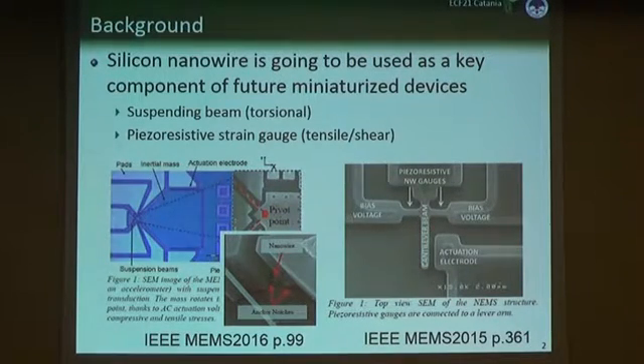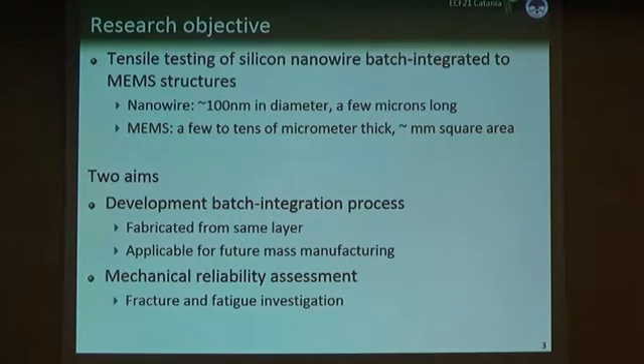In order to evaluate the structural integrity or reliability, we need to investigate the tensile fracture of these nanowires. So our research objective is to do a tensile testing of silicon nanowire, but this nanowire should be fabricated using a MEMS integration process, and also in the same layer as the MEMS structure is fabricated. In this research, the nanowire is around 100 nanometers in diameter and a few microns long, and the MEMS structure is a few or tens of micrometers thick,